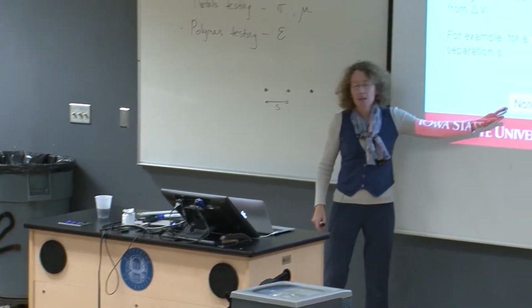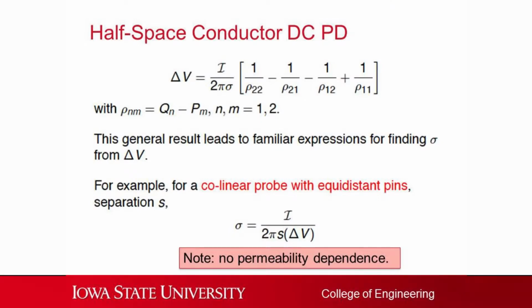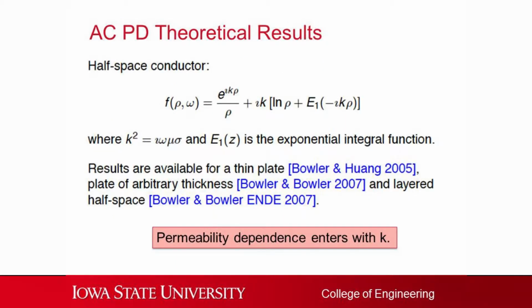One thing to notice here is even if you have a magnetic material, it doesn't feature in this equation, which is why we can use this to measure conductivity of ferromagnetic materials quite easily. So that's the DC regime.